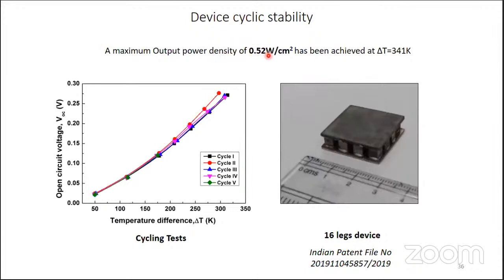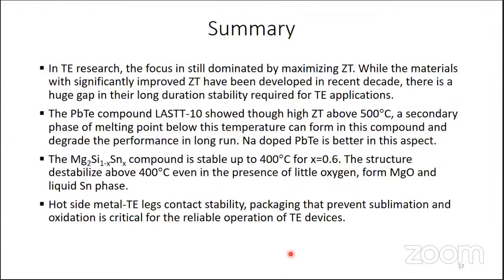So this device gives 0.52 watts per centimeter square power density at a 341 Kelvin temperature difference across the device, and it delivers a consistent open circuit voltage. This is for 5 cycles we measured, and subsequently we measured for long duration also. It is performing very well, and we filed a patent. This patent came up for review. We successfully defended, so it will be granted shortly to us. To summarize, this is the work I'm trying to present.